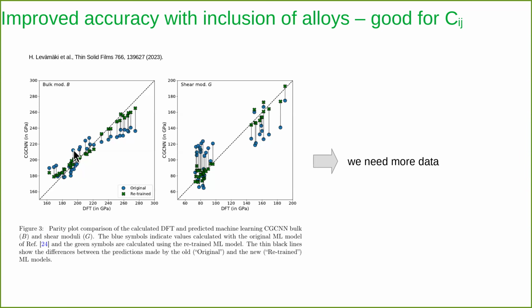The figure shows, in blue, the distribution of the error, the bulk modulus deviation from the DFT value, with our first starting CGCNN model, which was trained on the compound and Materials Project data. And then the green one shows that we have included a certain amount of new alloy data, validated against the rest of the alloy data. You see the error has been reduced significantly. So that helps us keep going, learn, and add more and more data to the database.